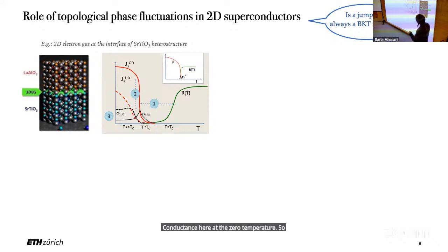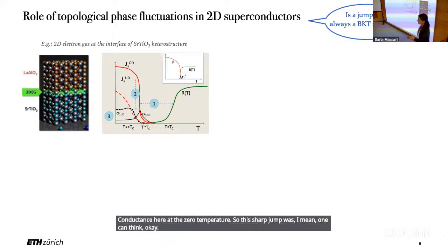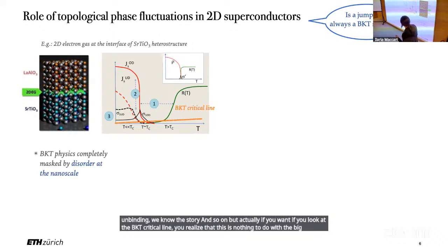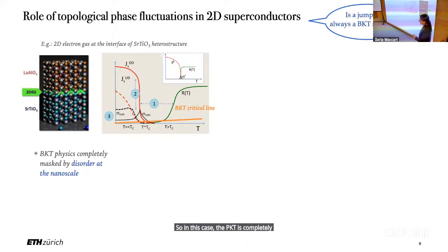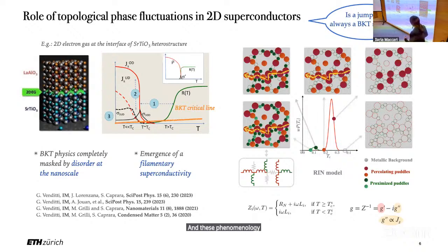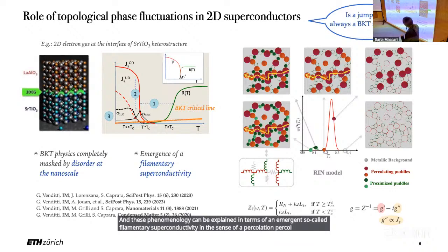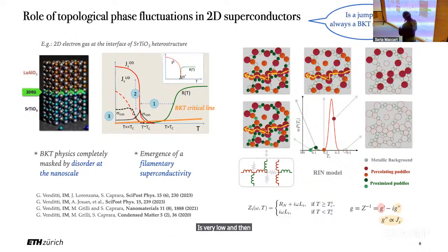So this sharp jump, one can think, okay, maybe it's just BKT physics, right? Because it's the unbinding, we know the story, and so on. But actually, if you look at the BKT critical line, you realize that this has nothing to do with BKT physics. In this case, the BKT is completely masked by the disorder, which is at the nanoscale. And this phenomenology can be explained in terms of an emergent so-called filamentary superconductivity, in the sense of a percolative transition where superconducting puddles in this very inhomogeneous system find, at a certain temperature, a percolating path that is very fragile, so the superfluid stiffness response is very low, and then it grows by many mechanisms. One of these is the proximity effect.